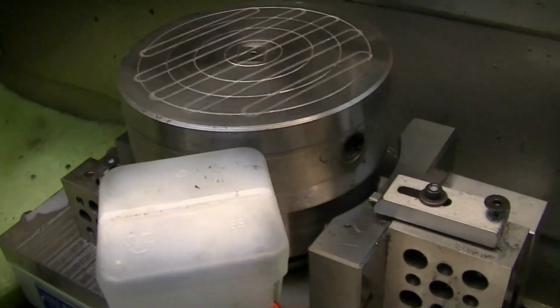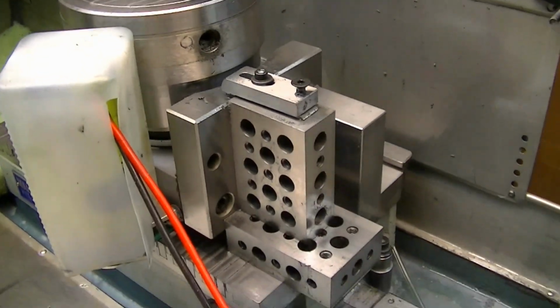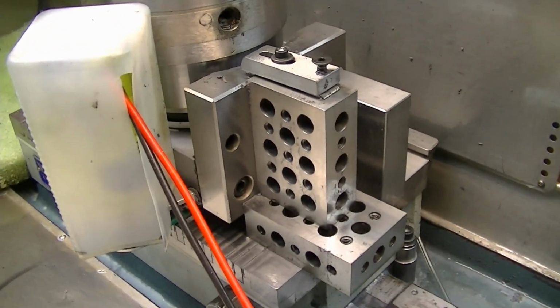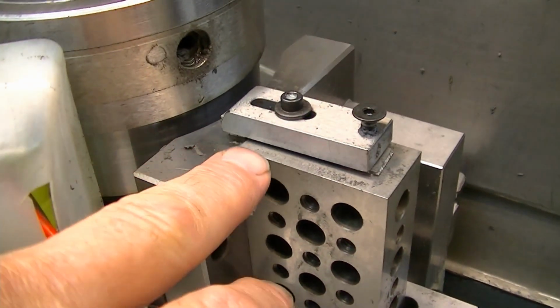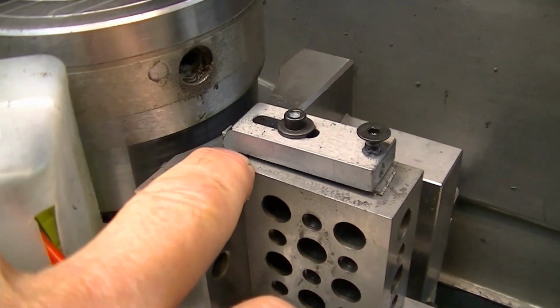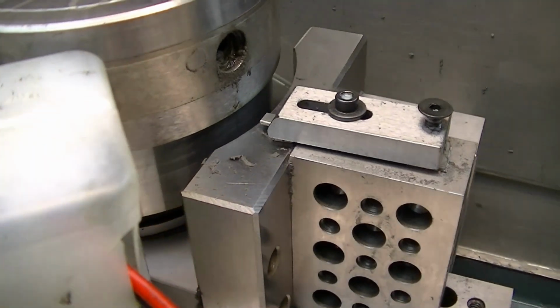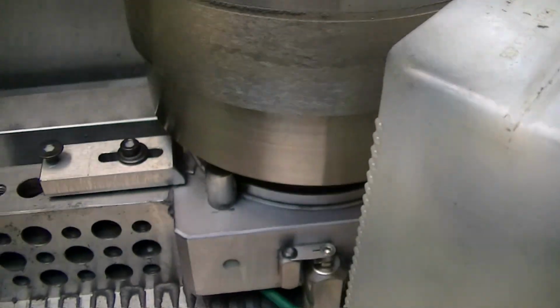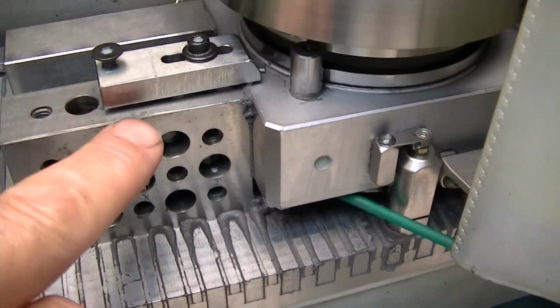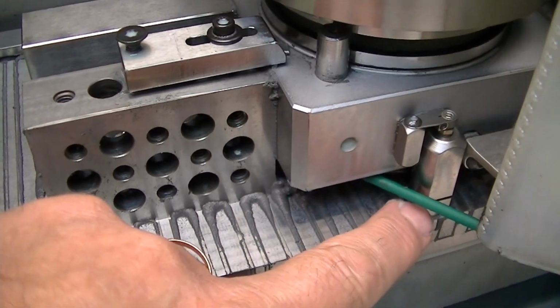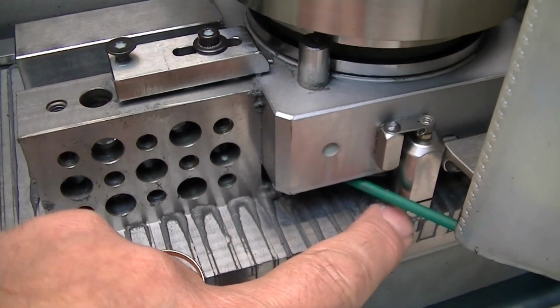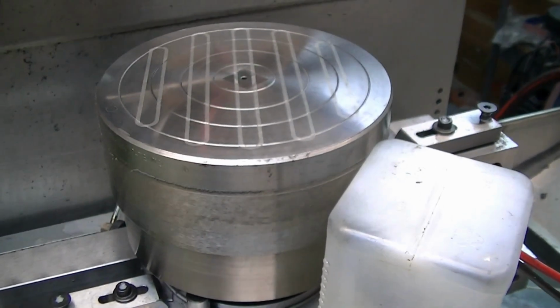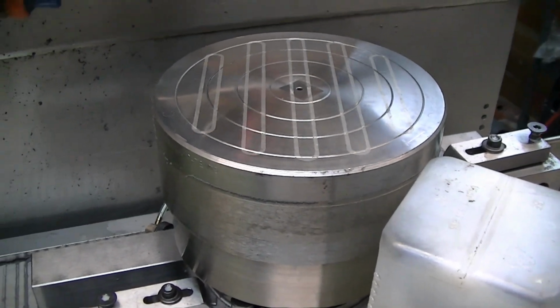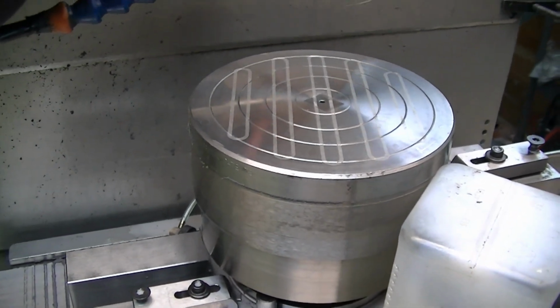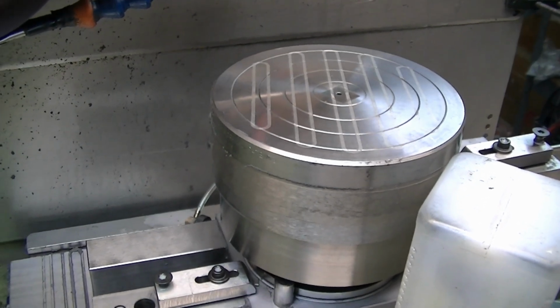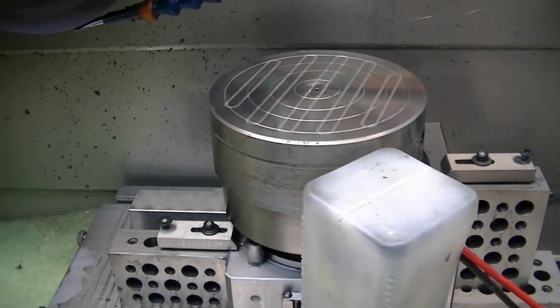Extra clamps on the punch grinder make it seat on the chuck a little bit more firmly other than just gravity, and that also blocks the grinder in so it can't skid on the chuck. And the differential screw setup that we have here on the back allows very precise tilt adjustments, easily 1 arcsecond or less, so that you can get it adjusted to get a very flat grind. In this case, it was easy to get within about 20 to 30 millionths flatness over that 5-inch diameter.